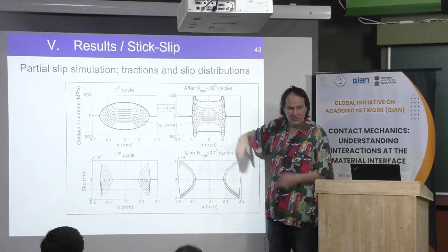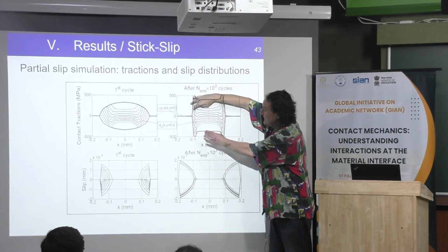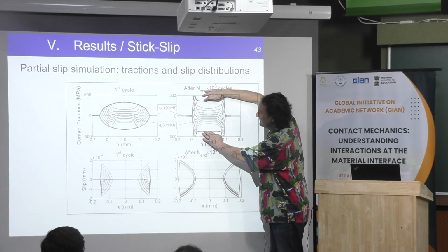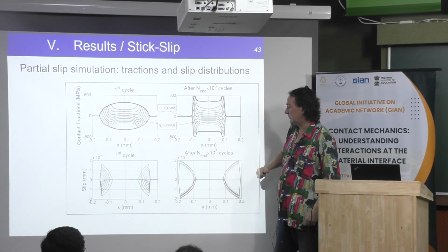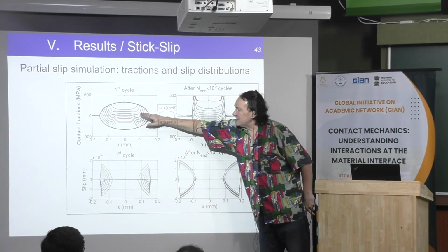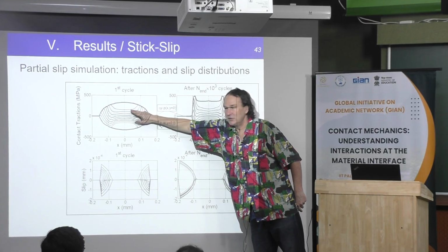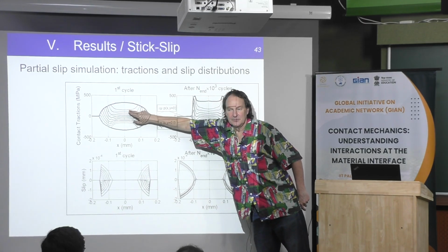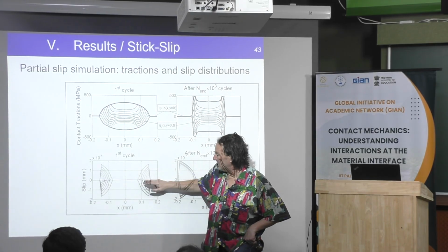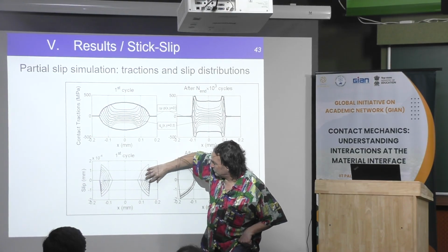Then, as we discussed in the car, the shear stress is always within the envelope. Qx is always between the minimum and the maximum pressure. And because you can see here that Qx is lower than the pressure times the friction coefficient, it means that here it is sticking. If it is sticking, there is no wear. Then here, there is no wear. The wear is only localized at the origin, here, and then it grows to the center.